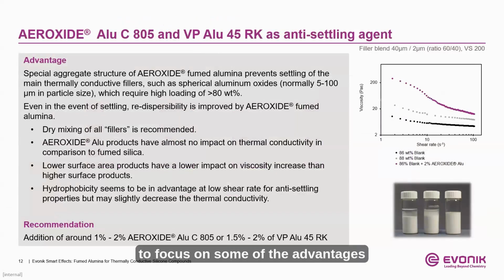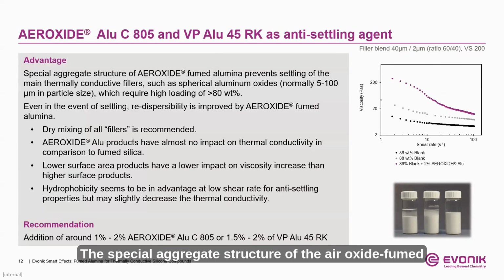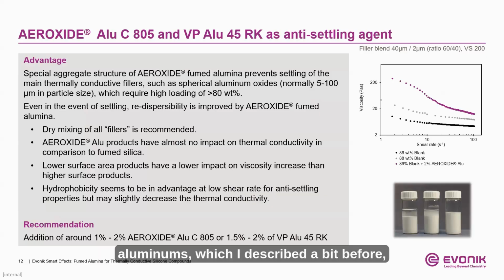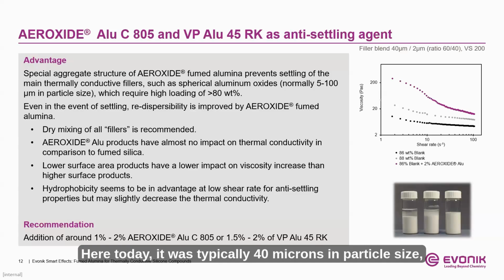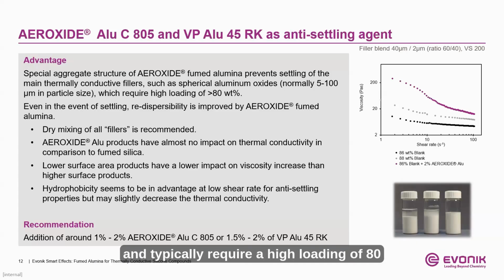So again, to focus on some of the advantages of the fumed alumina materials, the special aggregate structure of the AEROXIDE fumed aluminas, which I described a bit before, does work to prevent the settling of the main thermally conductive fillers, such as spherical aluminum oxides, typically 5 to 100 microns in particle size. Here today, it was typically 40 microns in particle size, and typically require a high loading of 80% or greater to achieve sufficient thermal conductivity values of the final material.